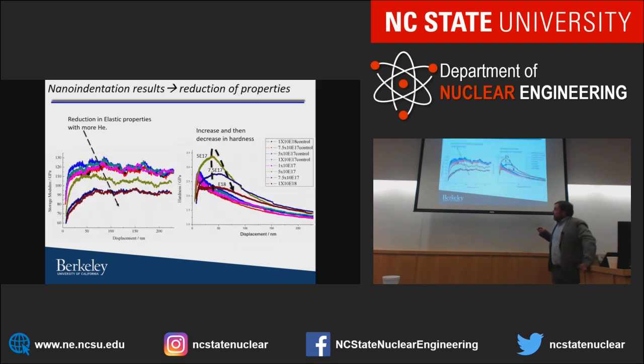If you do nano-indentation on those, we see that the elastic modulus actually goes down with those. Why is that? Well, if you form more and more bubbles, it's a composite. It's not dense material anymore. It's a foam eventually. Remember that picture with lots of holes in it? Well, it's a foam. And so the elastic overall property goes down because of this foam property.